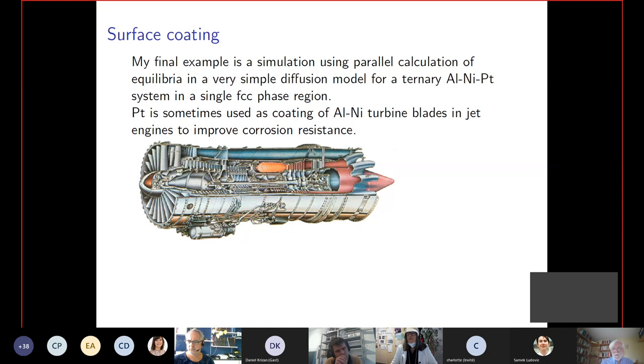But I also have an example where I'm using a very simple kinetic model. And I go back to this aluminium nickel alloy, where you have turbine blades in the jet engines here. And the turbine blades here are in a very difficult situation. When you are up in the air, the engine is working and you have very high temperature in this region, and then the plane will go down and you exit and everything cools down, and then the plane goes up again. So these turbine blades always circulate in temperature, high temperature, low temperature. And there are very few materials which can resist such kind of bad treatment without cracking.